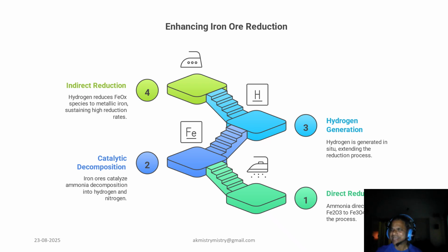Next, step 2 is catalytic decomposition. Here iron ore itself catalyzes the ammonia decomposition into hydrogen and nitrogen. This is a crucial step as it generates the reducing agent. This leads to step 3, hydrogen generation, where hydrogen is generated. Finally, step 4 is indirect reduction. The generated hydrogen then reduces iron oxide species to metallic iron, sustaining a high reduction rate. This integrated approach optimizes the reduction process.